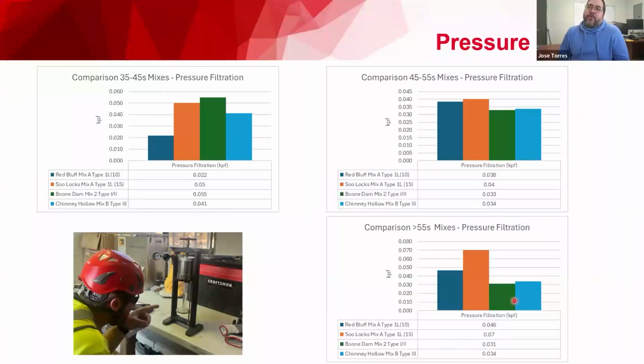And then we got a little bit more water squeezed out of the 1L10 and the 1L15. That was interesting—we're going to look at that some more. You expect these values to sort of go down, but they kind of came up from the 45 to 55 second range, and that only happened really with the 1L mixes. So there's something to look further into as we look at pressure filtration with the 1L mixes. They're behaving a little bit oddly once we start to get at higher viscosity ranges.